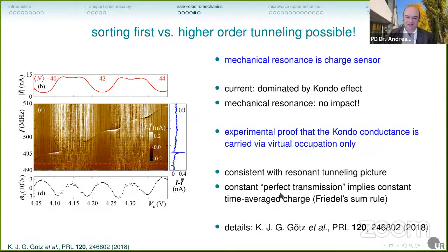Okay, this is a simplified picture, but I think it still captures the essence of what happens quite nicely. When the Kondo effect carries the current here, the electrons hop in and hop out so quickly that they don't contribute to the mechanical effects at all. It's also consistent with the resonant tunneling picture, because if you look at Friedel's sum rule, then a constant perfect transmission, as you expect for the Kondo effect, implies a constant time average charge in here. So apart from the higher order processes, this is not so much different from the Coulomb blockade area. Again, if you're interested, this is the paper. So this is a very nice example of what you can do with this mechanical resonance detection.